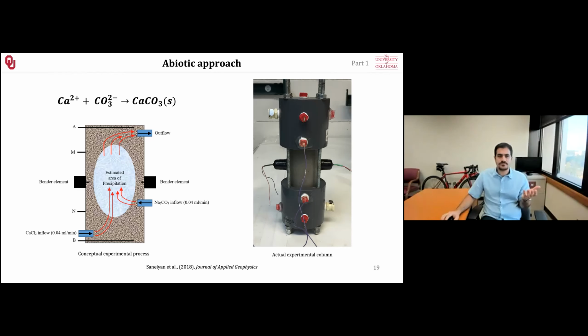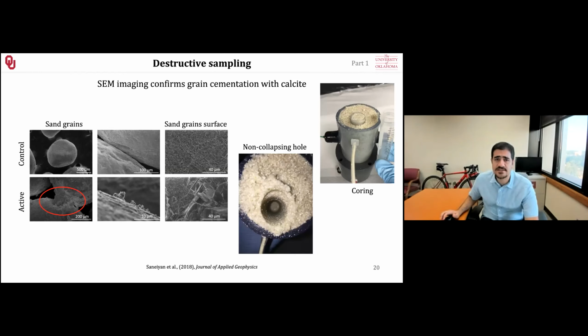To do so, we injected two different solutions, one calcium rich, one carbonate rich, and eventually calcite was precipitated inside our column. In the middle, we had both electrical electrodes on the sample holder as well as bender elements, and we were able to see that calcite was precipitated inside the column after about 250 hours of experiment, something like that.